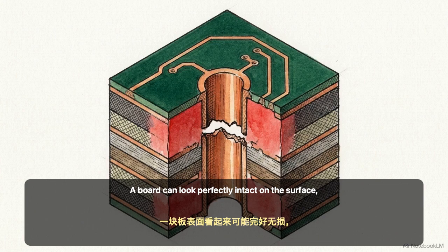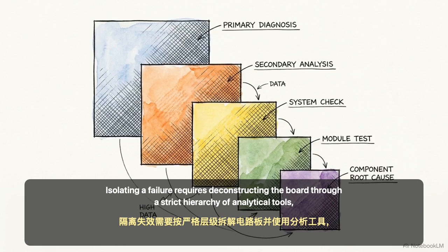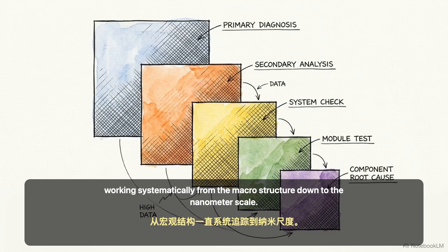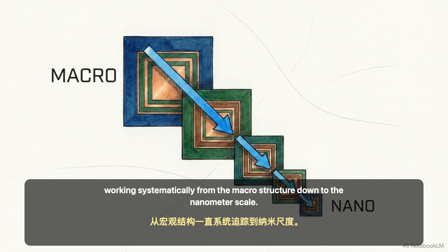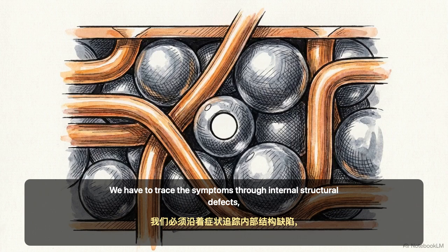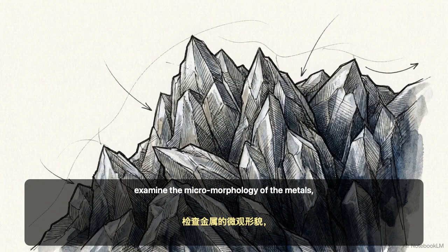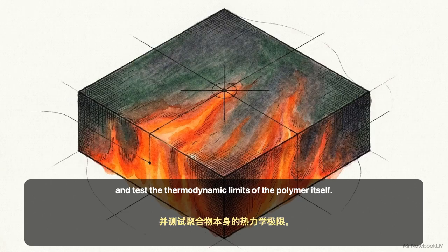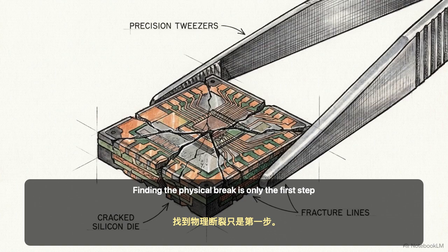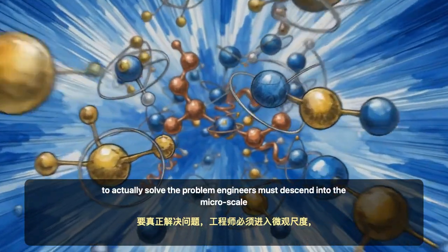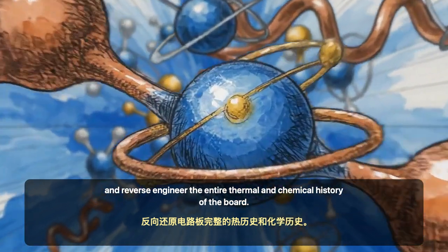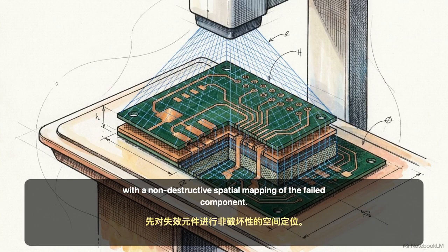A board can look perfectly intact on the surface while suffering from a fatal disconnect inside. Isolating a failure requires deconstructing the board through a strict hierarchy of analytical tools, working systematically from the macrostructure down to the nanometer scale. We have to trace the symptoms through internal structural defects, examine the micromorphology of the metals, analyze elemental contamination, and test the thermodynamic limits of the polymer itself. Finding the physical break is only the first step. To actually solve the problem, engineers must descend into the microscale and reverse engineer the entire thermal and chemical history of the board. The investigation starts at the macro level with a non-destructive spatial mapping of the failed component.